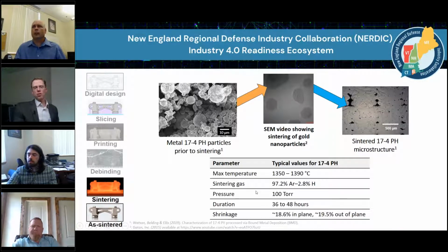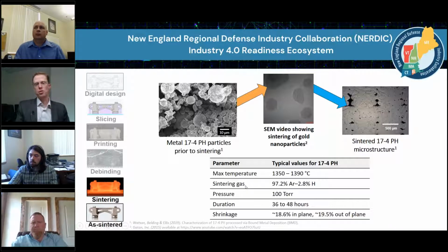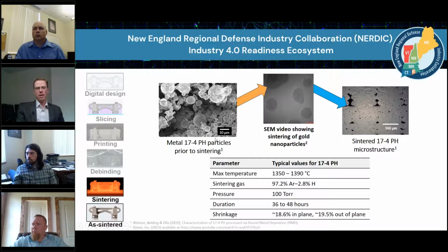So a couple of characteristics. The max sintering temperature is somewhere around 1350 to 1390 degrees C for a 17-4 PH, so right below the melting point. The sintering gas is an inert environment, argon with a little bit of hydrogen to remove any oxygen that happens to be on our particles. It's at 100 torr pressure. Typically, it takes about 36 to 48 hours, and you do get some relatively large shrinkage, as you might imagine.